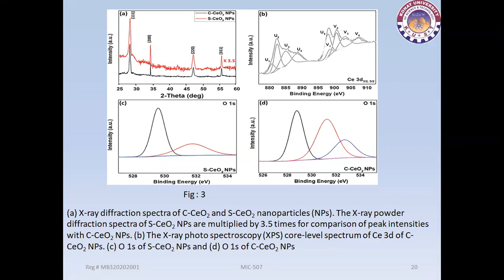The crystalline structure of the prepared spherical and cubical cerium oxide nanoparticles was observed by X-ray diffraction studies and the corresponding spectra are depicted in figure 3a. The major peaks located at 28.3, 33.48, 47.34 and 55.76 theta were indexed to the 111, 200, 220, and 311 planes of the cubic crystalline phase of cerium oxide with space group Fm3m 225. However, the peak intensities of spherical cerium oxide nanoparticles were significantly lower than cubical cerium oxide nanoparticles. Therefore, their intensities were multiplied by a factor of 3.5 for comparison only.